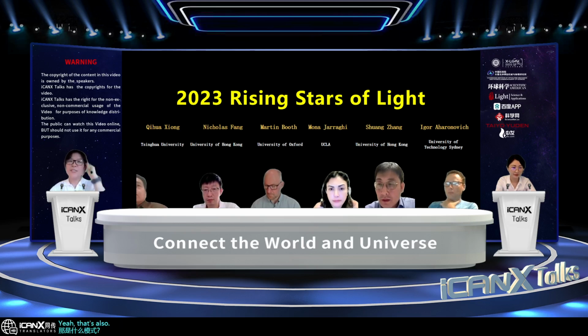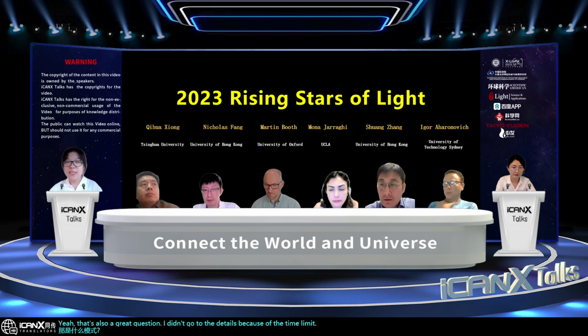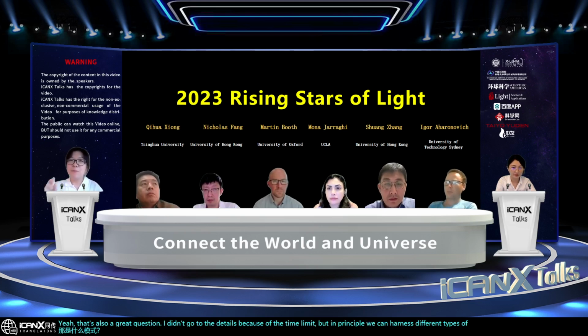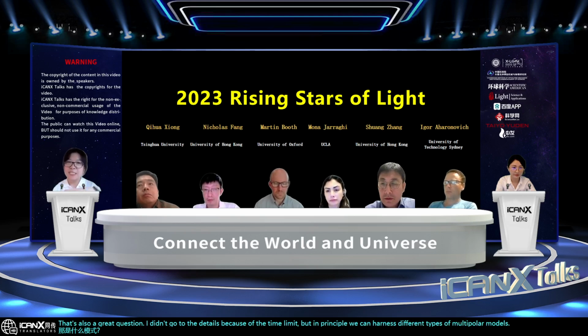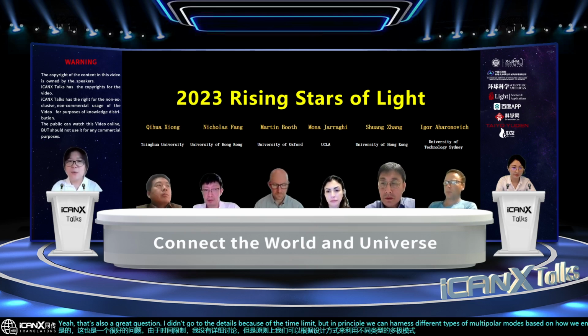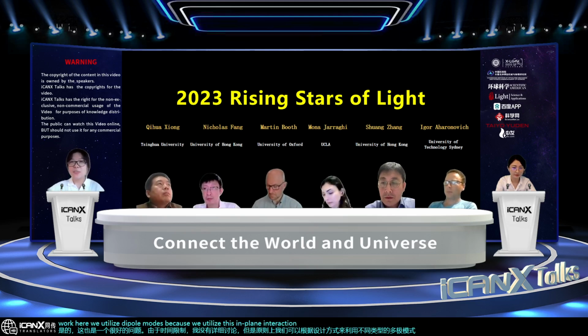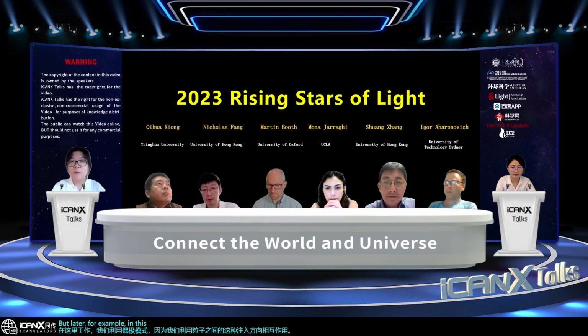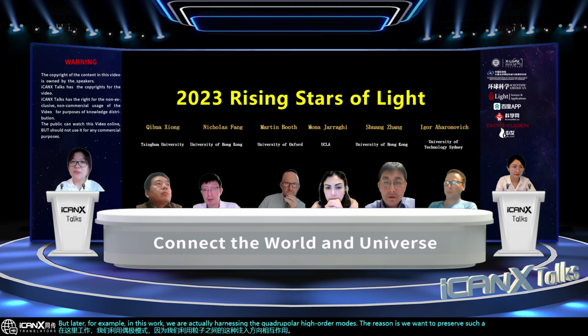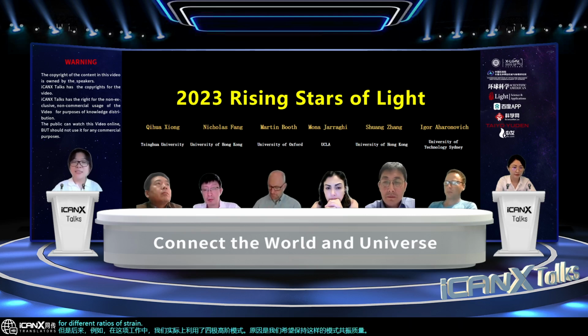Yeah, that's also a great question. I didn't go to the details because of the time limit, but in principle, we can harness different types of multipolar modes based on how we engineer the structures of this lattice. In the very early work here, we utilized dipole modes because we utilize the in-plane interactions between particles. But later, for example, in this work, we're actually harnessing the quadrupolar high order modes. The reason is we want to preserve such a mode resonance quality over different ratios of strain. And we found the high order modes give us a pretty stable mode quality under the different stretching ratios here.